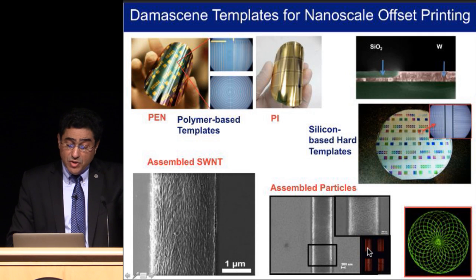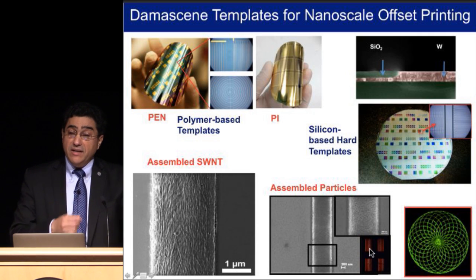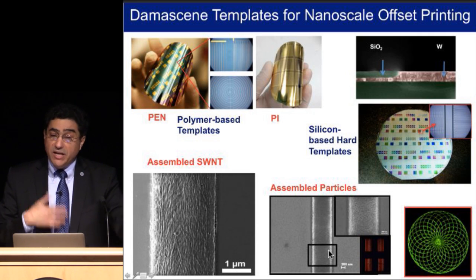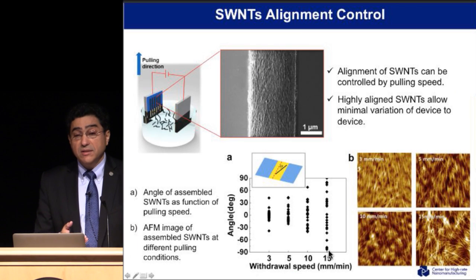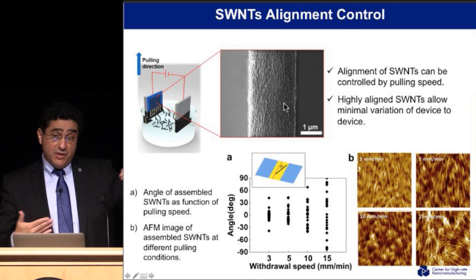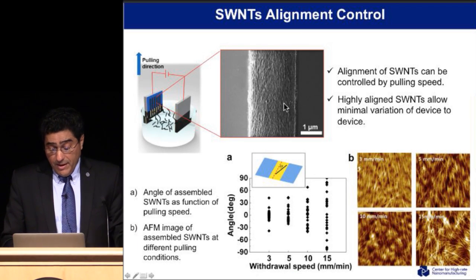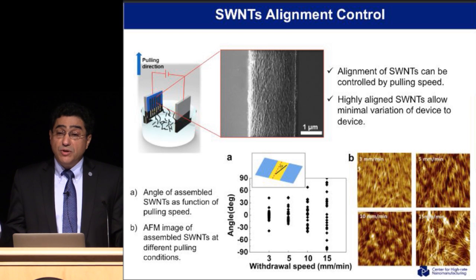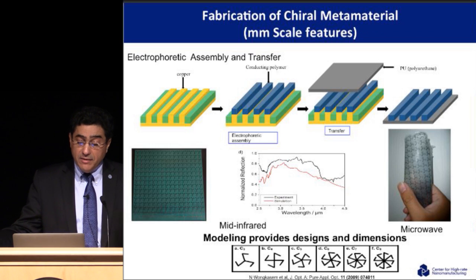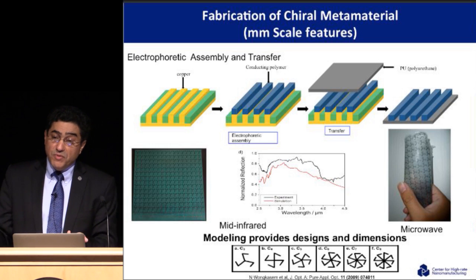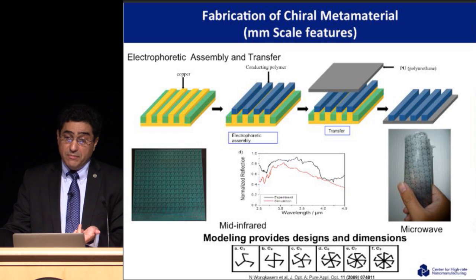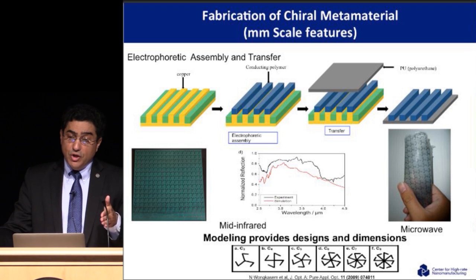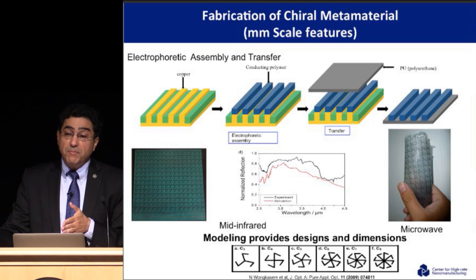Okay, and you can also have a lot of other advantages like aligning the nanotubes. So when you align nanotubes, you get more properties. You get more conductance. You get more strength out of them if you're building a structure, for example. And the process actually can be much, much more in terms of the scale. So I showed you 15 nanometer scale. This is millimeter scale. This is 2 millimeter scale, 3 millimeter, 5 millimeter scale. So the process can do nano, micro, or macro, or all of them together in the same template.